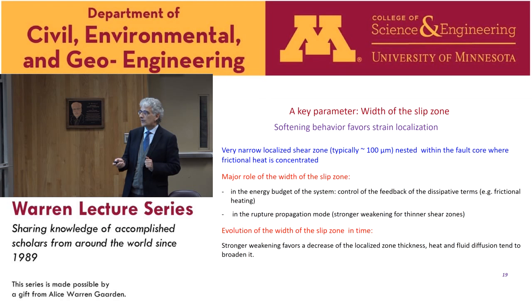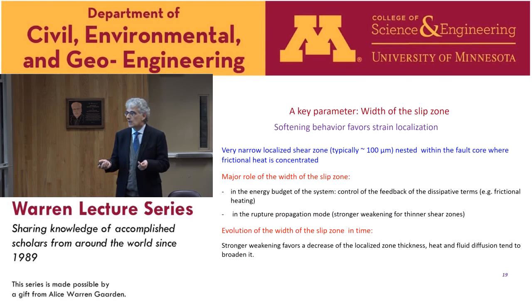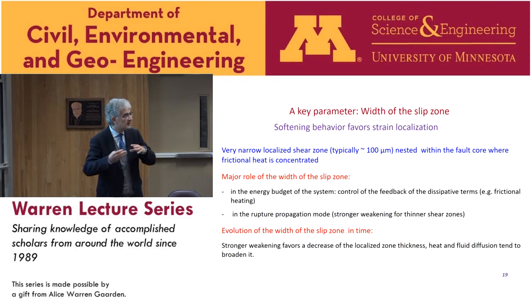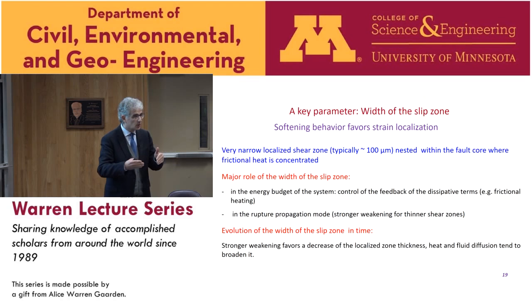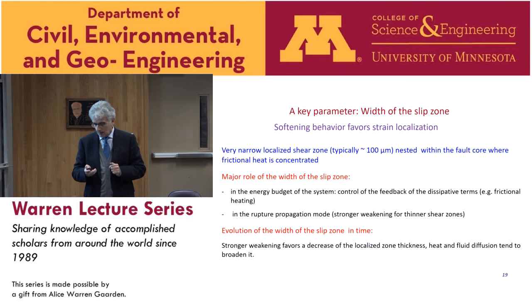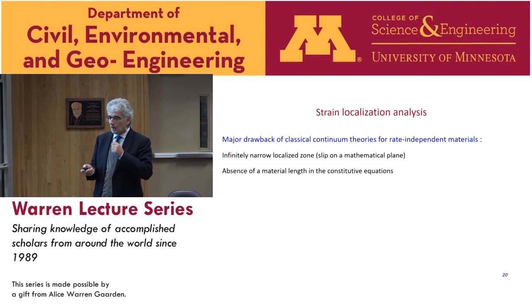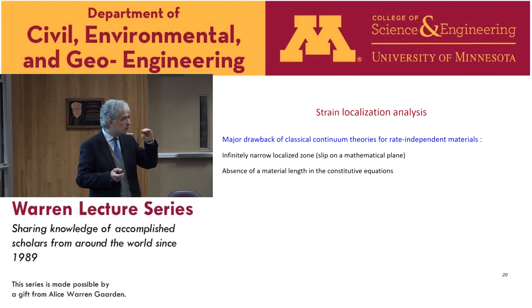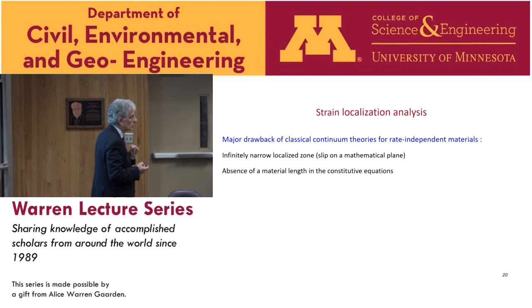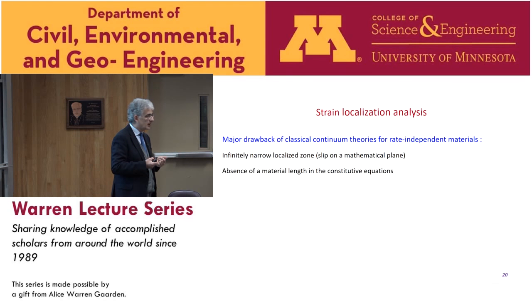And the width of this slip zone will evolve in time because stronger weakening will favor a more localized zone, whereas heat and fluid diffusion will tend to broaden it. So localization here is a whole process where localization and possibly delocalization is also possible. This we'll see in some computations later. So the actual thickness and the evolution of the thickness of the localized zone should come from a proper strain localization analysis, and for that we have to have the good tools.